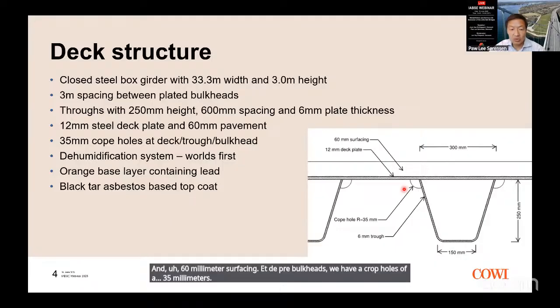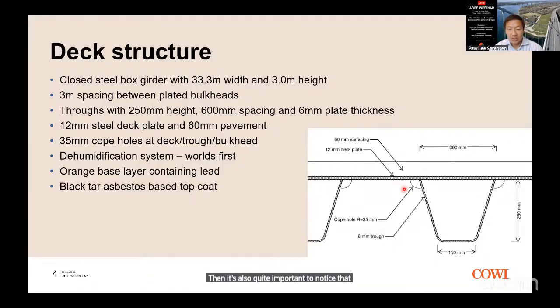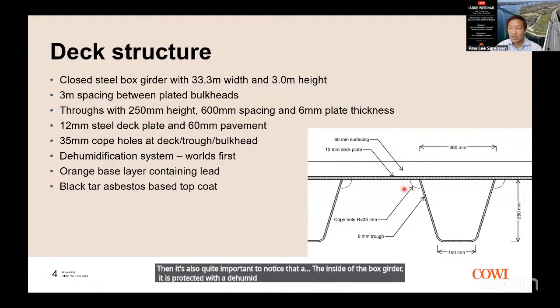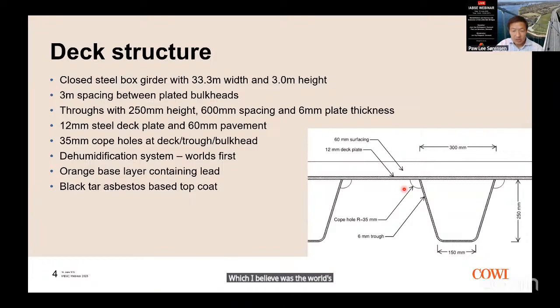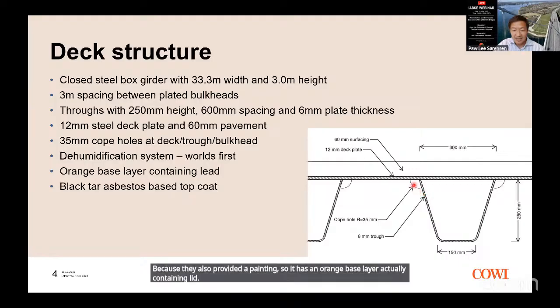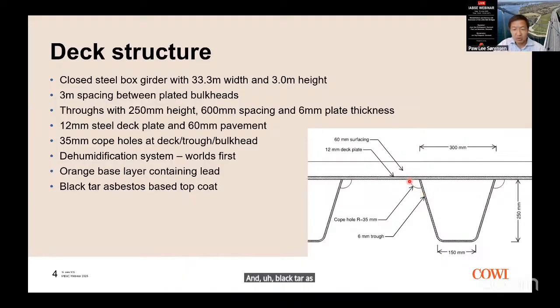Then it's also quite important to notice that the inside of the box girder is protected with a dehumidification system, which I believe was the world's first. And despite having this dehumidification system, you could say that maybe the designer didn't trust it as much, because they also provided painting. So it has an orange base layer, actually containing lead, and a black tar asbestos top coat. So it's indeed very well protected for corrosion on the inside.